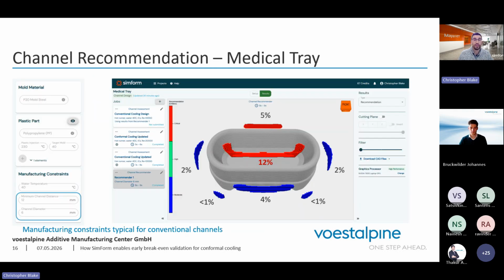So now we can look at the first simulation that we did for the medical tray. And for this one, we used typical manufacturing constraints for conventional gun-drilled channels. In this case, it was a 6 millimeter diameter for the channels, or about 1/4 of an inch, and a 12 millimeter offset, or about 1/2 an inch offset. You can see on the screen the offset of those recommended regions from the surface of the plastic part. You can also see the relative cooling demand of each of those regions.